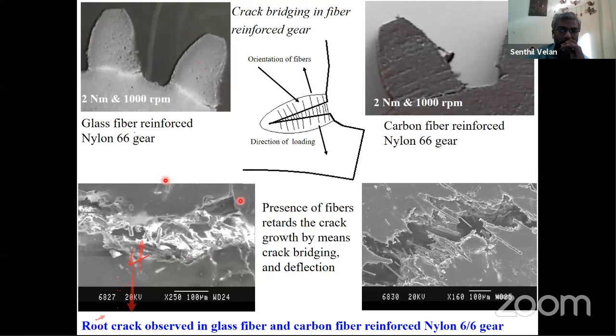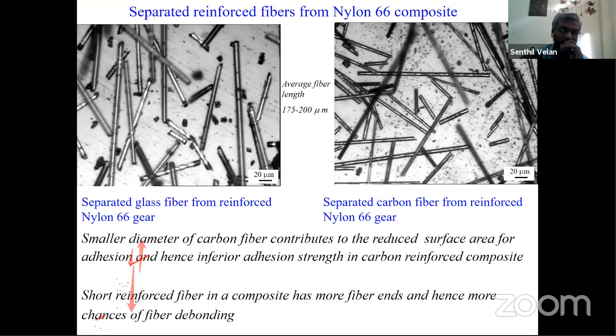But what was a surprise was, we were thinking that by having a carbon reinforced material, because we know that carbon is a better, superior material than glass, you expect a better fatigue strength. This is what we expect. But surprisingly, in fact, we had a poor or inferior behavior. So it is not just the base material.